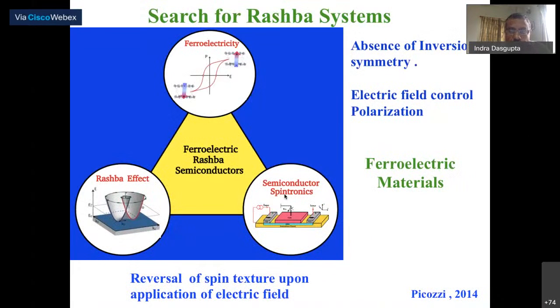Well, so the first thing is that, of course, we have to search for Rashba systems. As I told you, one of the key ingredients for Rashba systems is that they have to break inversion symmetry. And we would like to look for Rashba effect in bulk systems. One of the key materials for such systems can be ferroelectric materials. Ferroelectric materials are intrinsically insulating, and not only that, they have to break inversion symmetry. So you essentially have the criteria to sustain Rashba effect getting satisfied for ferroelectric systems.